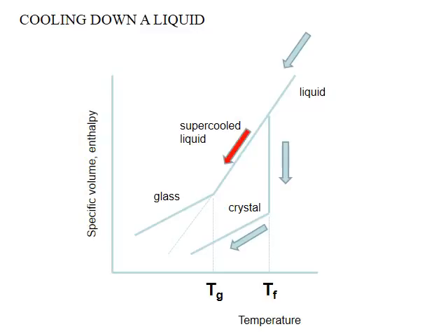How many degrees under Tf the liquid may be cooled will depend on the liquid viscosity, and the viscosity will depend on the liquid structure, which we do not know, by the way. Water, for example, can be supercooled a few degrees below Tf. Melted silica, highly viscous, can be supercooled thousands of degrees.